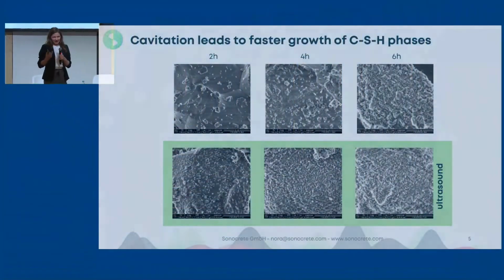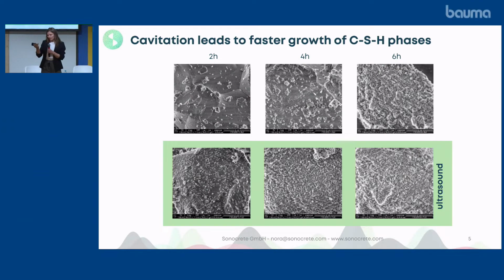The other thing is that in order to make concrete hard, there are CSH phases growing in it. So it's basically like little fingers that are growing and interlocking. And with the ultrasound, we induce cavitation. That's basically imploding bubbles. And when these bubbles implode, they create high pressure and high temperature. And this is an optimal seeding place for the CSH phases.